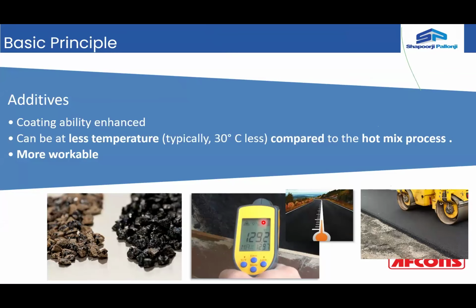Now, when you talk of additives, coating ability is enhanced. You can produce the mix and lay the product at a lesser temperature, typically 30 degrees less, and it can be more workable. If you see the photographs, the normal, uncoated aggregates, and then the coated aggregates, this is basically the effect of the Evotherm mixed in the asphalt.